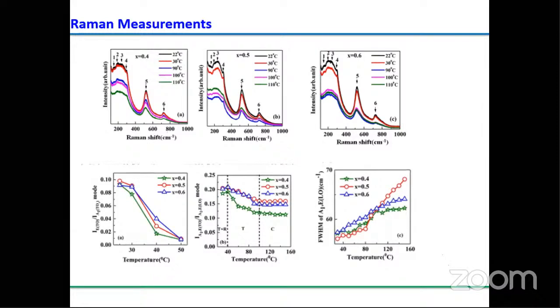So what we can conclude here: below 40 degrees, these materials have the tetragonal and rhombohedral morphotropic phase, up to room temperature, 40 degrees. After 40 degrees you have only tetragonal phase. After 100 degrees, that is what we call the ferroelectric phase transition, tetragonal to cubic. Here we will not get perfect cubic, we will get pseudo cubic. They behave like a cubic, but still they are not perfect cubics. That phase we call the pseudo cubic.